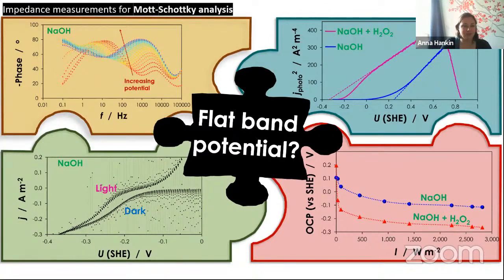So making impedance measurements at the interface between the hematite and the solution, and using that to do what's called Mott-Schottky plots, so capacitance, inverse of capacitance squared as a function of potential. And then another method is Gartner-Butler analysis. So you measure photocurrent as a function of potential, square it, and the intercept should give you the flat band. But of course, that's only valid if the photocurrent that flows obeys the original prediction. So the prediction doesn't include either of the two recombination modes. So that's out.